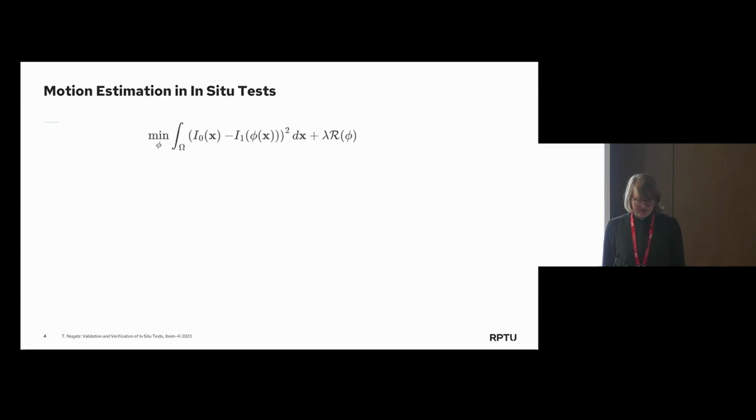And we just heard about DVC, but in general, you can split all of the motion estimation algorithms into a distance measure and a regularization, also the classical DVC ones. Now, in regularization, classical DVC methods put their focus on subdividing the image domain omega. We had this with the subvolumes just now, and the transformation, which can be fairly general, but you saw in the last talk, displacement is, for example, one that is very commonly used.